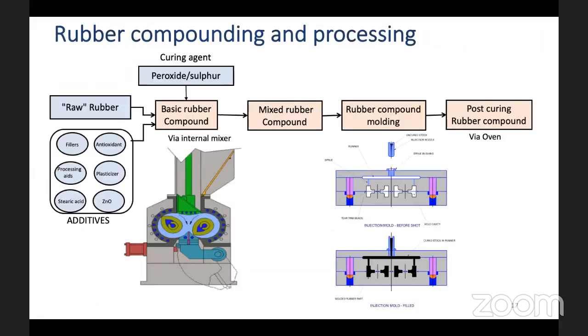So what you basically do, this is the main process. You take different additives, that is antioxidants, plasticizers, fillers, processing aids, and curing agents, and then you mix rubber with these additives in a mixer. In the rubber industry, it is called a Banbury mixer, an internal mixer. And then you also add the curing agent here. Then you get a mixed compound.